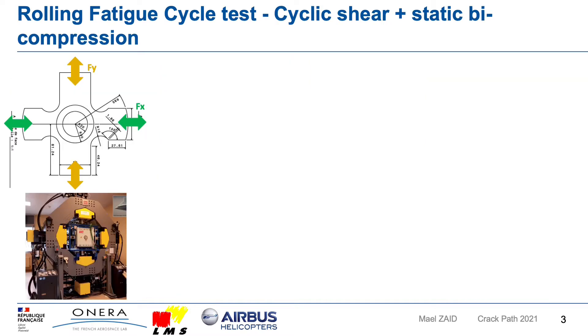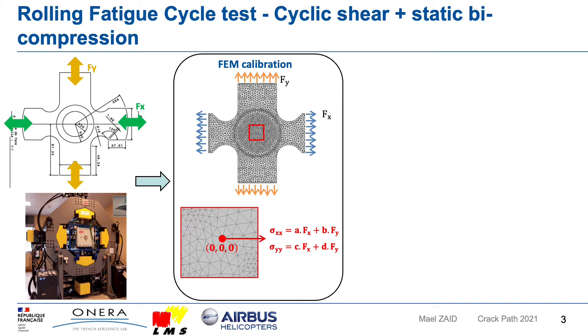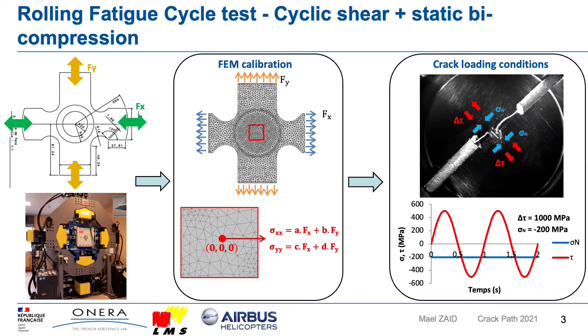The proposed procedure is based on force-controlled loading. A sinusoidal function is applied to the arms of the specimen to submit the crack to a cyclic stress with a static biaxial compression. To obtain the loading condition, a previous elastic finite element computation is performed by applying pressure as boundary conditions to identify the relationship between the stress tensor components and the boundary conditions to be applied to the biaxial testing machine. This calibration step allows us to precisely control the crack loading condition and submit it to a cyclic mode 2 plus a static biaxial compression.